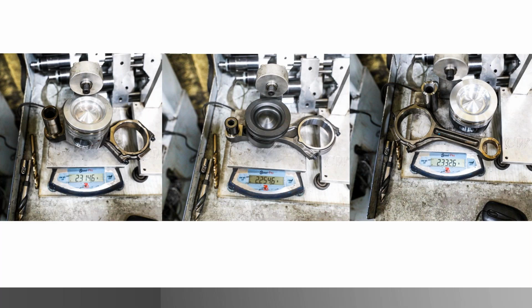There is a big problem that I see on the new blocks. Let's say you bought a new block from Ford, and you only need the block, or you tell them it's for 2014. I don't know if they're going to transition away from that, but currently they're not. What they're doing is machining that block. Now, we said that there was a steel piston there, right? Well, the expansion rate of steel and the expansion rate of aluminum are completely different. Anybody that's been a machinist for 5 minutes can tell you that. Your piston wall clearance needs to accommodate that piston, whether it's aluminum or steel. The problem is they're not doing that. They're machining it for one diameter, for one piston. Guess which one? Yeah, the steel piston. They're not really worried about you if you're running a cast aluminum piston.